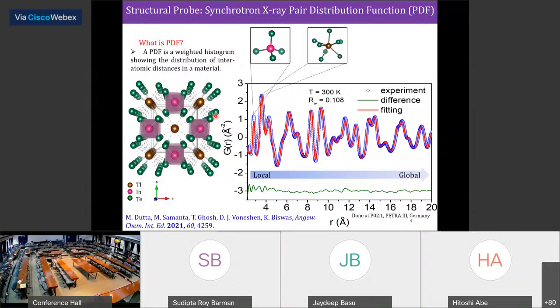The second peak comes due to this thallium telluride bond distance, which is a weak ionic interaction, and the third peak is basically the third nearest neighbor. This local structure can be visualized if we analyze these three peaks properly, and the global structure can be analyzed if we analyze the higher R peaks, and both cases are fitted fairly well.